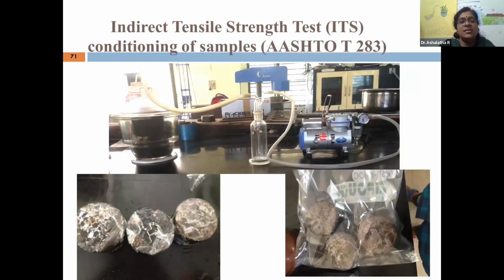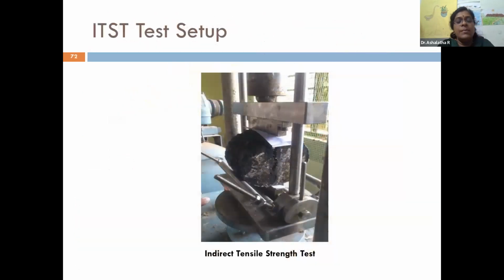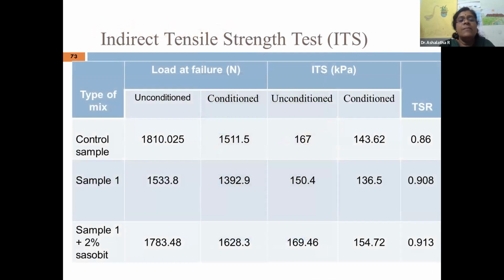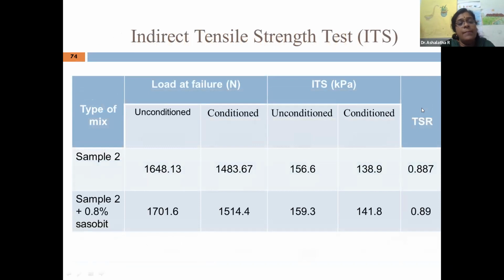And this is the indirect tensile strength test, the condition of the sample. This is what we did in our laboratory. This is the indirect tensile strength test photograph, and this is the compilation of the results for the control sample, that is the virgin mix, sample 1, where only RAP is there, and the second case RAP with 2% Sasobit. So we found out the load at failure for unconditioned and conditioned samples, and TSR values were calculated. The same exercise was done on sample 2 also, and TSR values were calculated.